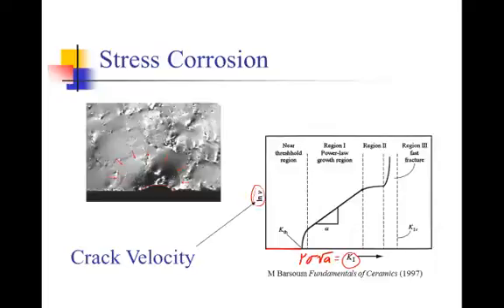And at the same time, I'm showing here the surface of a piece of dental porcelain that was fractured in my laboratory. This fracture surface has on it a set of arrows showing a halo-like appearance around this original flaw marked with a red oval on the surface, and that flaw grew slowly over time, more and more rapidly, until it reached the critical stress intensity factor, and then it suddenly accelerated and grew rapidly through the material.